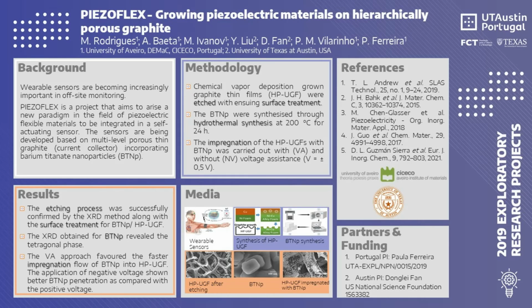The foam impregnated with no voltage exhibited a much slower impregnation flow, and there was a conglomeration of particles at the top of the foam, indicating that there wasn't an undisturbed penetration. Both voltage-assisted foams demonstrated a faster impregnation flow and fewer conglomerates at the top, demonstrating a more distributed penetration.